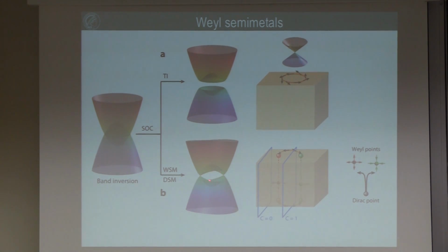If we have Dirac points like in graphene, we can even generate Weyl points by time reversal symmetry breaking—if we apply a magnetic field, we should split a Dirac point into Weyl points. Or if we strain or remove the inversion symmetry in a crystal, we also get two Weyl points. The Weyl points are distinguished from the Dirac point because they have a chirality, and this makes many of the properties more interesting.